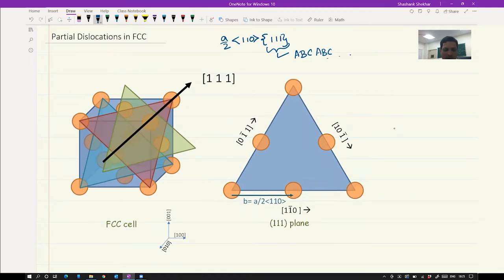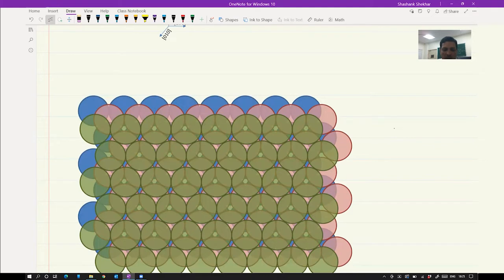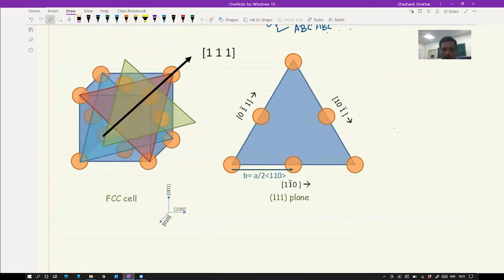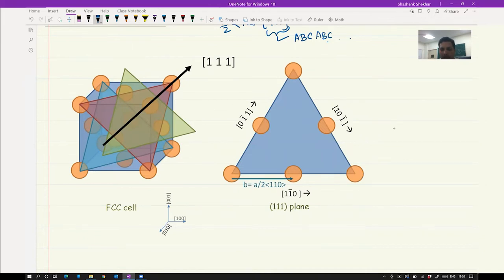The {111} planes are marked and you can clearly see that there are three different arrangements of atoms. If you look at it, the three arrangements in terms of atoms — A, B, and C — are clearly different; A and C are not the same. So there are three layers ABC when we look at a {111} plane. We know the Burgers vector is a/2 <110>, which lies on one of its edges. The shortest translation is a/2 <110>, so when an extra half plane forms, it must move from one point to the next.